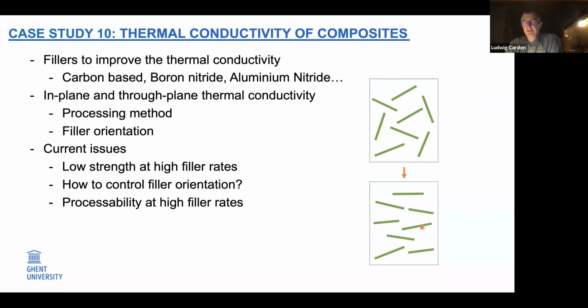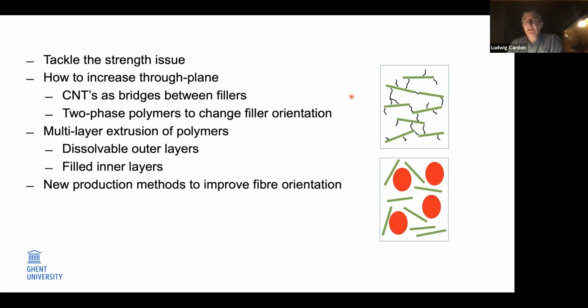So we have the fibers oriented like that, then we know we have a very good heat transfer in the horizontal direction, but in the through plane, it's not good. Can we optimize this? Oh, yes. We do what we call a multiple blend of fillers. An example we highlight in this case: you can work with one type of filler, for instance graphite flakes combined with some carbon nanotubes, or, like you see at the bottom, we combine that with so-called spherical fillers. This can be glass fillers, or air bubbles. We also tried that by foaming the whole system.